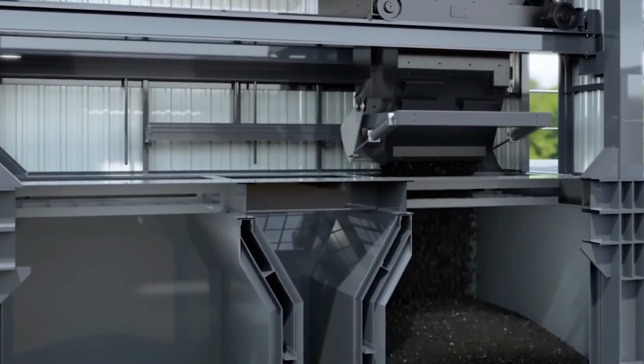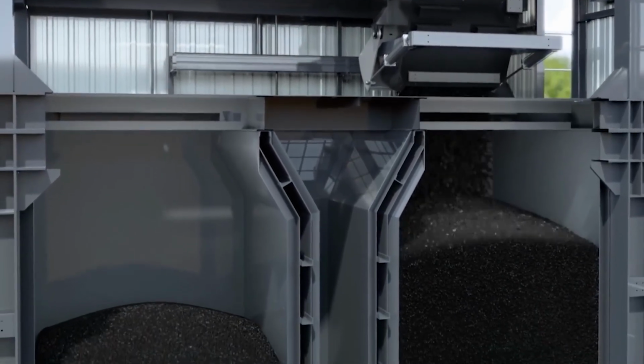Dust to binder ratio. The airflow must be balanced. If the return ratio drifts high, the mix becomes dry and brittle, leading to cracking. If it drifts low, the mastic becomes unstable and soupy. The plant automation constantly adjusts the draft to maintain this balance.